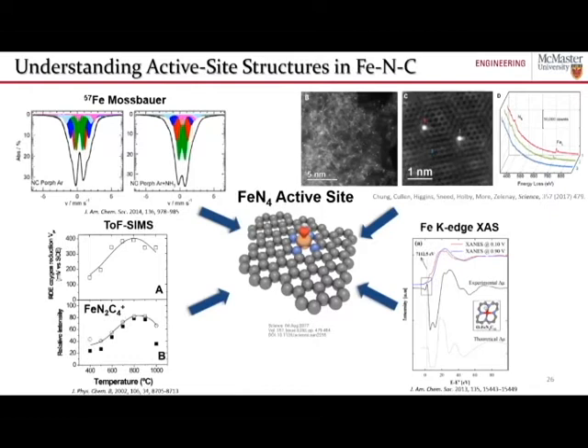But any electron microscopist will tell you that contamination with things like silicon, things like iron, can really cause a lot of problems and can cause you to misinterpret those atoms as being your catalytically active structures. So what we were able to do, working with Oak Ridge National Lab, is not only image these bright spots that we attributed to being these iron centers that were active for catalysis, but we were also able to do location-specific electron energy loss spectroscopy and see that there were simultaneously present these iron atom species with nitrogen in the near vicinity that helped us further confirm our hypothesis that these catalysts consist of these iron nitrogen 4 active sites embedded within a carbon matrix.